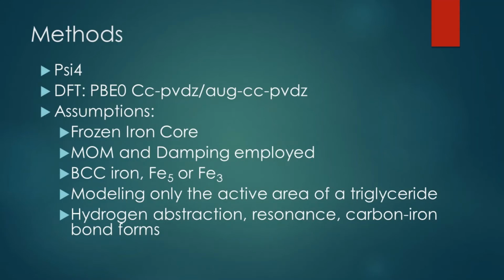The PBE0 is a hybrid generalized gradient approximation which mixes PBE and Hartree-Fock exchange energy in a 3-to-1 ratio, and it can provide good energy estimations for metals, although it can often overbind. The aug-cc-pVDZ, or Augmented Correlation Consistent Polarized Valence Double Zeta for long, adds a diffuse d orbital to heavy atoms and a diffuse p orbital for H atoms.